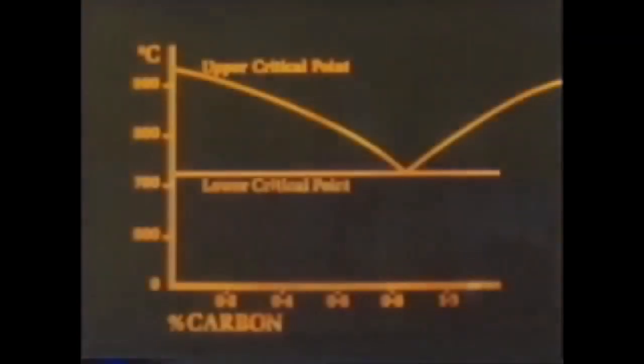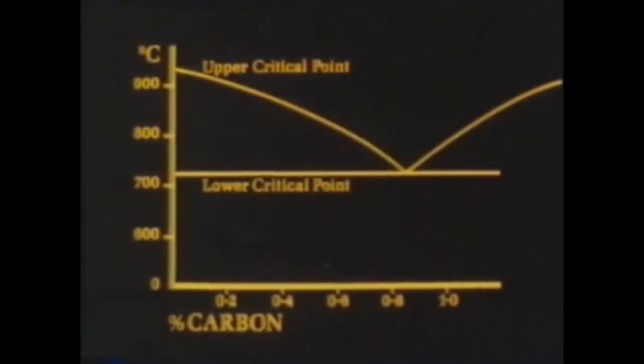It's worth looking at the iron-carbon equilibrium diagram to see the effect of these conditions on this mild steel ring. Because carbon has very little solubility in the low-temperature, alpha form of iron, carburizing must take place at a high temperature just above the upper critical point, where the solubility of carbon is greater. As the material is very low in carbon, this means quite a high temperature. This, with the time in the furnace, will determine the depth and penetration of carbon into the surface of the component, as seen in this cold cross-section.